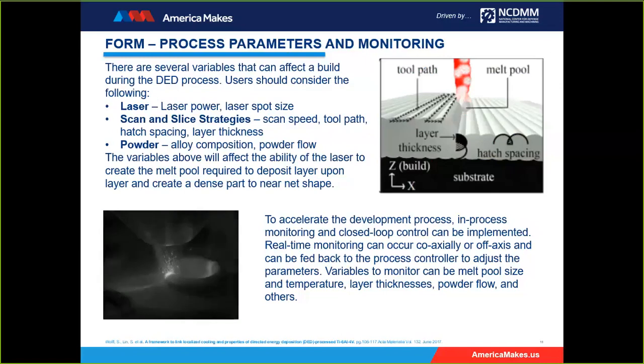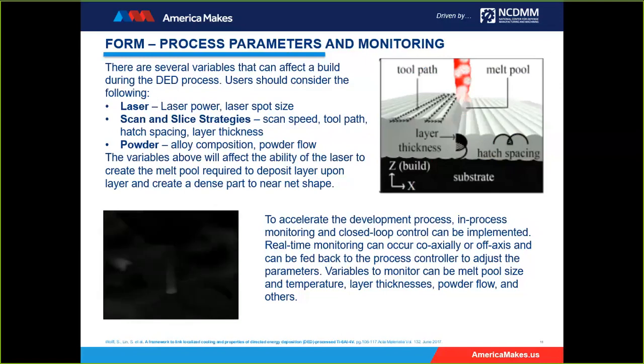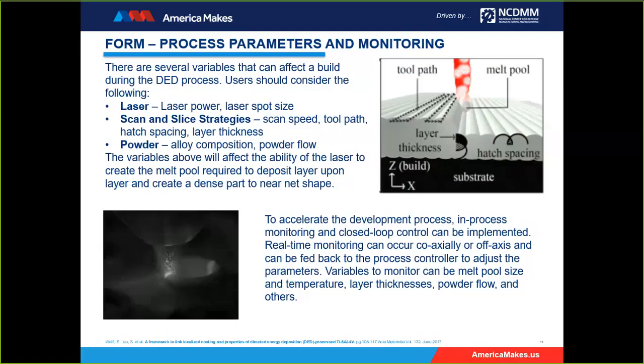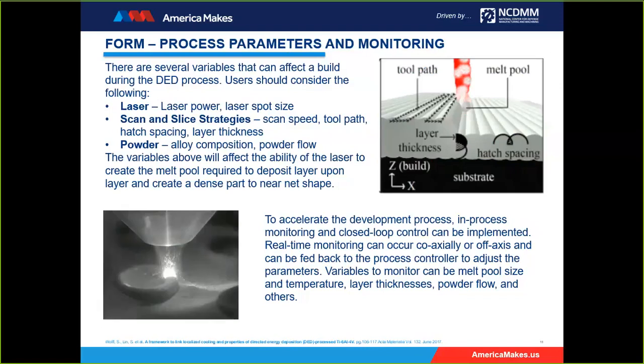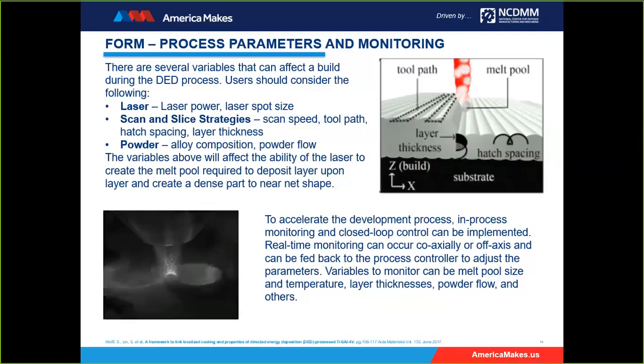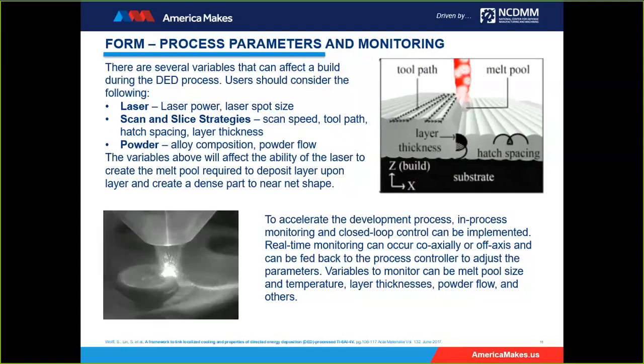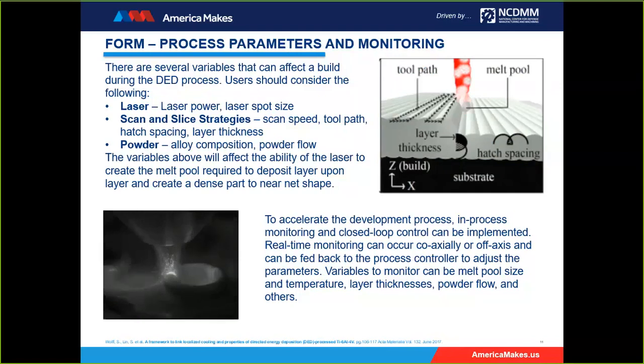To accelerate the development process, there is a suite of in-process monitoring and closed-loop control features that can ensure high-quality parts. The DED process can incorporate coaxial or off-axis measurement devices to monitor the DED process and potentially feed the signal back to the controller and adjust the parameters during the build. Examples of variables that can be monitored are the melt pool size and melt pool temperature, the layer thicknesses, the powder flow, and others. To the left, you'll see an off-axis camera monitoring, and it features a real-time view of the deposition process and the powder flow.